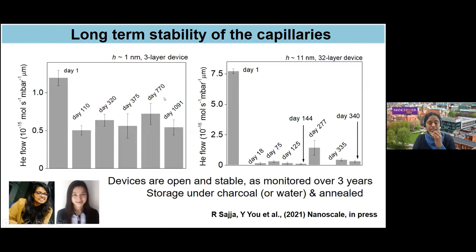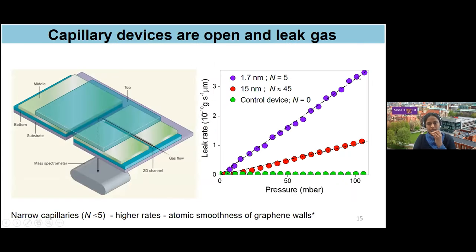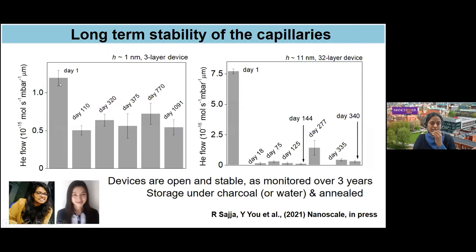These devices conduct for a very long time, which is an important aspect. We monitored our capillaries for gas leaks from day one through three years. Even after three years, the conduction — indicated by the slope of the measurement curve — remains very good, with only some reduction in flow. This long-term stability makes shipping samples to collaborators and enabling a lot of collaborative work quite feasible with these capillaries.